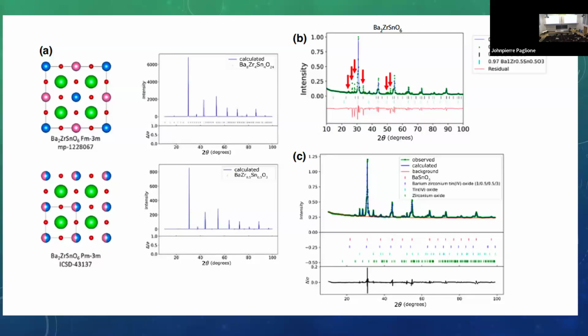Okay, one more example here. Again, we have this predicted new compound, predicted to be a perovskite structure with ordered cations. This is a known compound here with disordered, smaller unit cells. X-ray patterns are pretty identical. Their fit is absolutely terrible. We made it fit with some impurity phases, which is a lot better using the known materials. So it's very, very obvious it's no new compound.